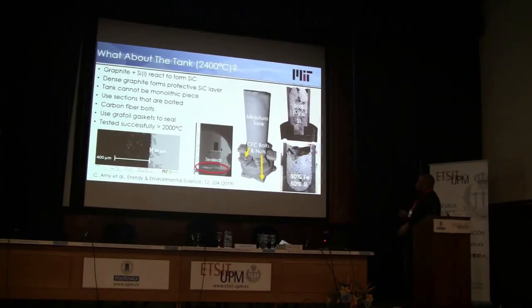But what we do is, and it took us a few times to get it right, we put a piece of graphoil there, so it's a flexible form of graphite. It's all graphite, it's all carbon, so it's fine to operate at the temperatures of interest. And we essentially compress down on that seal. So when we press down on the seal, it forms a tight connection. And when we put the silicon in there, the silicon, of course, wants to react with even that graphite seal, but that reaction is expansive. And so it actually fills the gap, and the silicon carbide essentially plugs itself, and the silicon is not able to continue to get out.